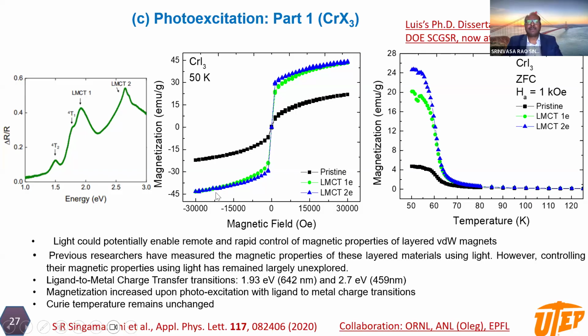And we conducted magnetization measurements on this compound, and you see that the black curve shows the pristine behavior of chromium iodide at 50 Kelvin. It is a ferromagnetic phase. Upon shining light with the 2 different wavelengths separately on 2 different crystals, you see the magnetization, particularly the saturation magnetization, jumped up in both cases. That is consistently observed in the temperature-dependent magnetization as well. So upon photoexcitation of this compound, the saturation magnetization went up with the 2 independent excitations, 1.93 electron volt and 2.7 electron volt. However, we saw that the Curie temperature remained unchanged in both cases. So only the saturation magnetization increased upon photoexcitation.